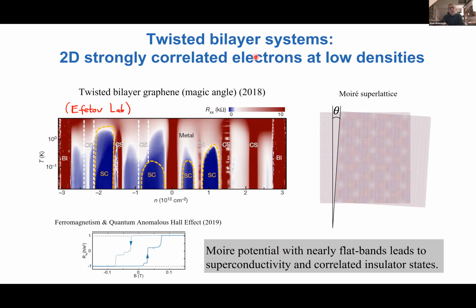And I guess it goes without saying that the most spectacular result in this field is obtained in magic angle twisted bilayer graphene. And this goes back to 2018, the results of Pablo Jarillo-Herrero, which was followed up by a large number of groups with outstanding results demonstrating in one material intertwined superconducting phases, correlated insulator phases, as well as quantum anomalous Hall effect, and so on. So what is really amazing is that using a gate, one can change the electron density in the same material and explore different quantum states